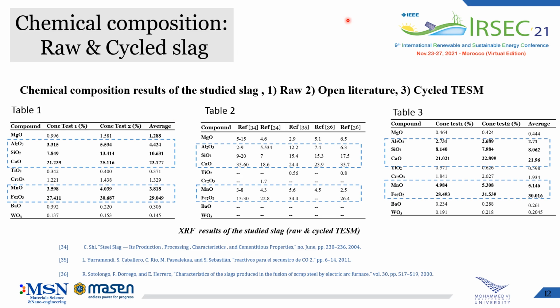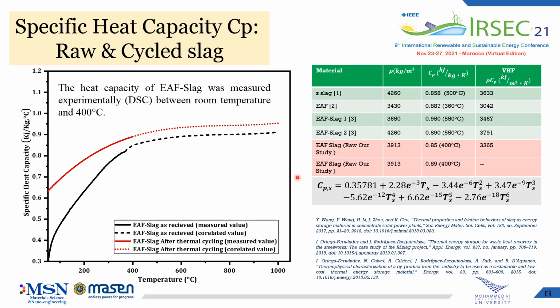We have measured also the specific heat capacity experimentally using DSC technique between room temperature and 400 degrees C, and we found a value of 0.85 kJ per kilogram Kelvin for the raw material. This value increases a little bit after thermal cycling to reach a value of 0.89 kJ per kilogram Kelvin. And due to the limitation of DSC technique at 400 degrees C, the result was correlated.